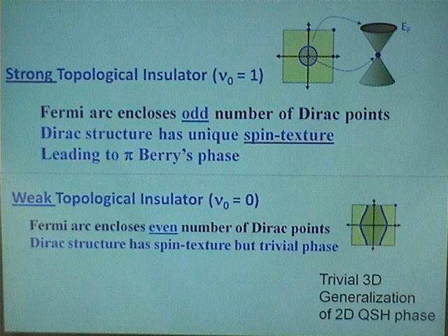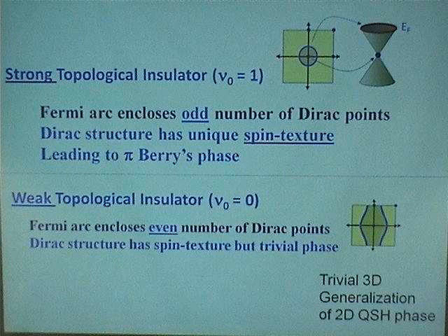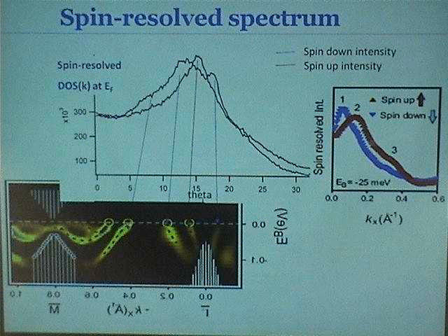So then we just find an odd number of states between two Kramers points, and we need more evidence than that, although in theory, Z2 theory, that should be enough. If we can prove that the states are singly degenerate, because if they're doubly degenerate, then the 5 would double into 10, and then there is no Berry phase. How do I prove that the states are singly degenerate and there is a Berry phase on the surface? So that's a critical step.